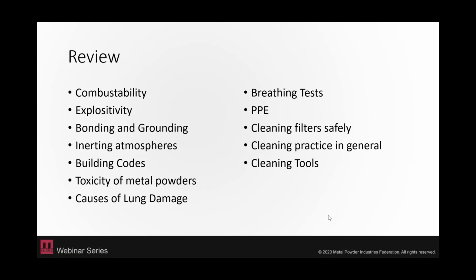Yeah, sure. So we don't use water to extinguish, but we can use water to react the surface of a powder. So for aluminum in a wet vacuum, it actually does move through the water to form that oxide layer, which is then stable. So I guess you could see it as kind of a stabilizing thing. And I'm actually not aware of the difference for an aluminum filter, air filter, and a laser powder bed. But yeah, that is definitely something to consider.